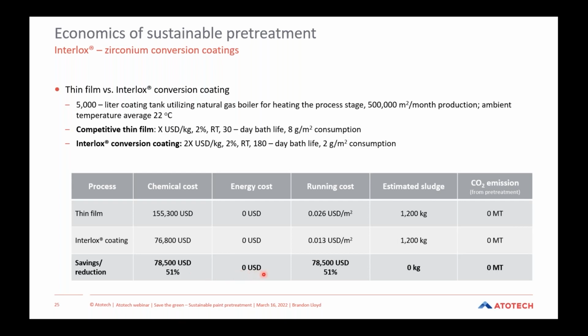Here we see that for both processes, because they're operated at ambient temperature, they have zero energy cost associated with them. So the total running cost differences are coming exclusively from the chemical costs. But here you can still see that we're able to reduce that by about 50%. The estimated sludge or byproduct, again, is going to be similar. And then again, the CO2 emissions from the pretreatment itself will be identical because of the ambient temperature operation in the conversion coating step itself.